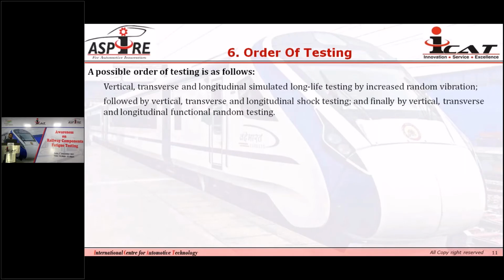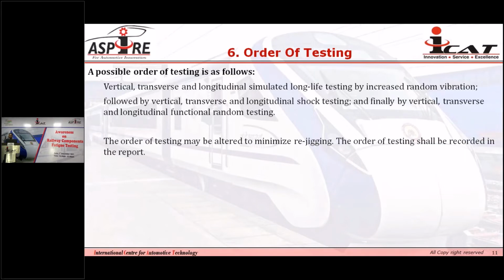So vertical, transverse, and longitudinal simulated long life testing by increased random vibration, followed by vertical, transverse, and longitudinal shock testing, and finally by vertical, transverse, and longitudinal functional random vibration testing. Actually, this is the possible order which defines the standard, but one line also in the standard says the order of testing may be altered to minimize the rejigging, and the order of testing shall be recorded in the report.